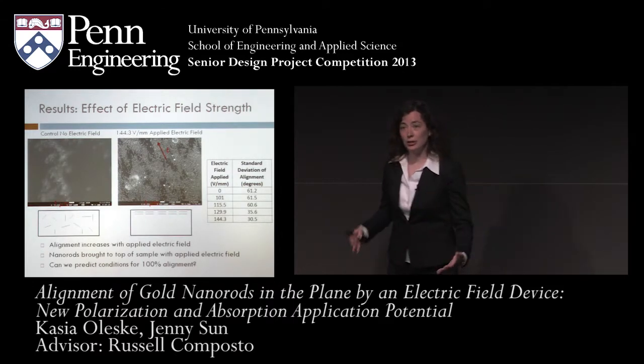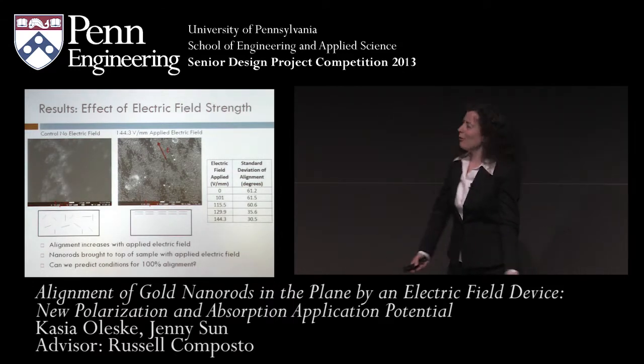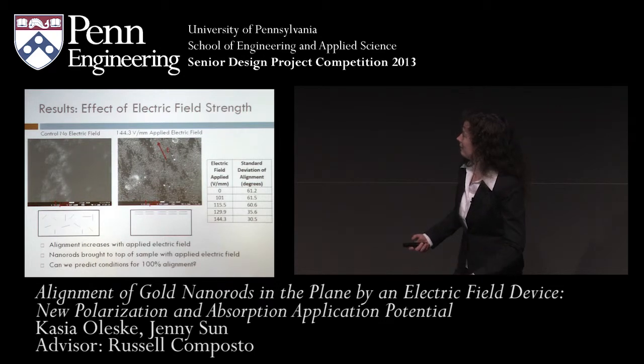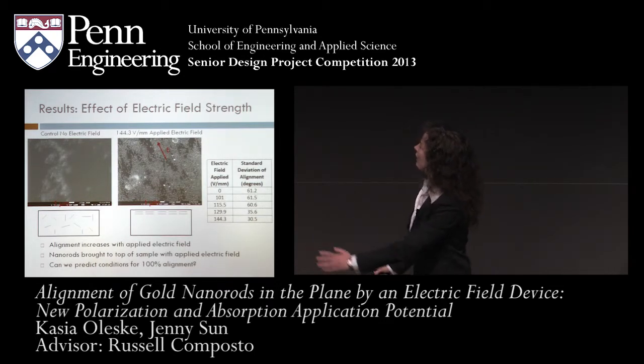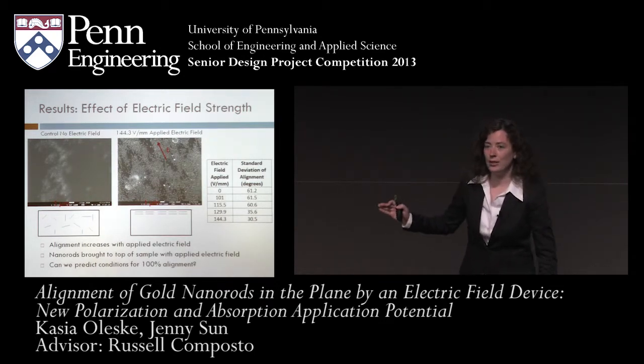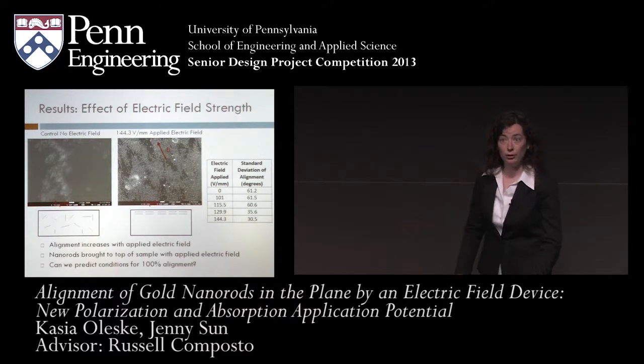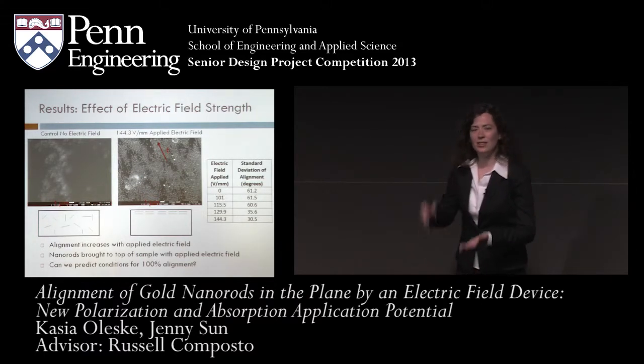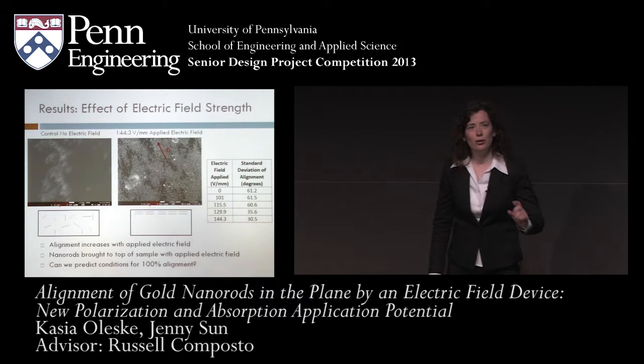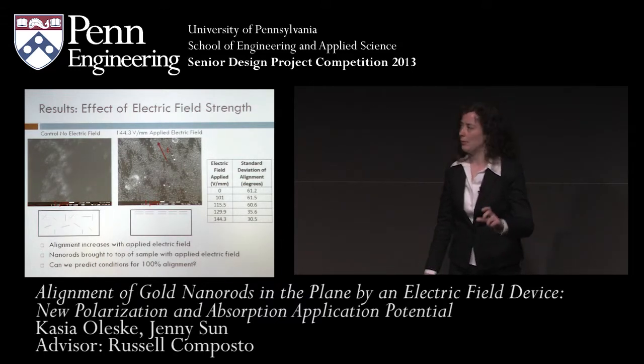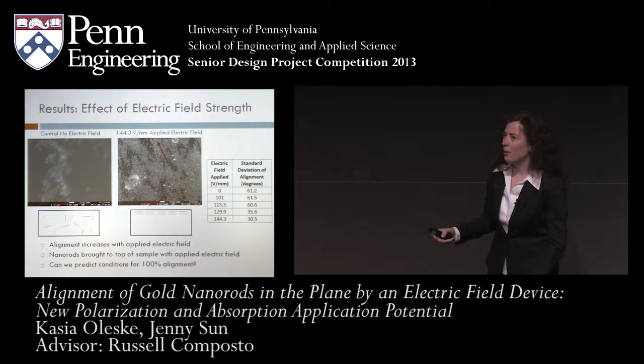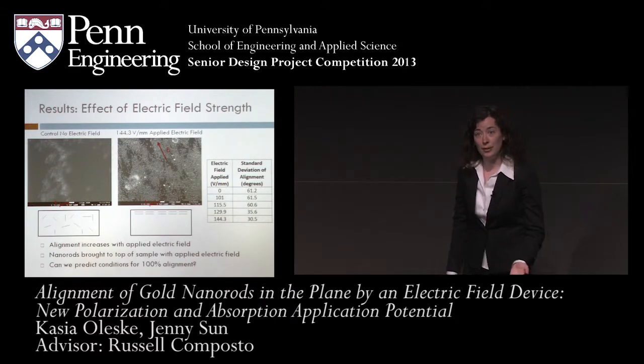So our major study was seeing, hey, what's the electric field have to do with alignment? If we increase electric field, does that increase alignment? So as you can see, on the left is a SEM image of the control sample with no electric field applied. And in SEM, it's a top view of the sample, so you're only looking at 50 nanometers deep. But our samples ended up being about 100 to 200 nanometers thick.